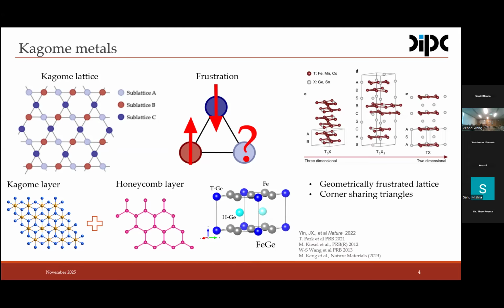Here I show the structure of iron germanium, 1-1, FeGe. This is the simplest Kagome metal we can find. It has the same structure as FeSn, and we see that the Kagome layer is formed by the iron transition metal ions in this plane, separated by the honeycomb germanium layer. One can understand the whole family of Kagome metals by piling up these Kagome layers, stacking them along the z direction. For the 1-1 material, we have the simplest unit cell with one Kagome layer separated by the hexagonal honeycomb layer. But if we increase the ratio of the transition metal with respect to X, where X is germanium or tin, we can form the whole family of Kagome materials, ranging from the 166, which essentially doubles the 1-1 FeGe or FeSn, and then stacking or interleaving several honeycomb layers.